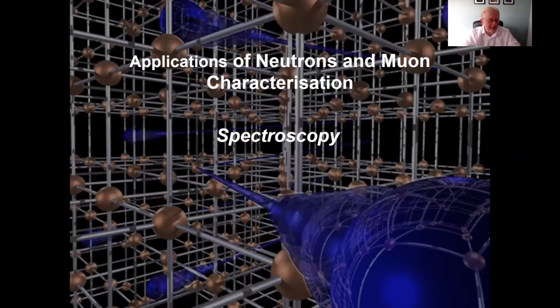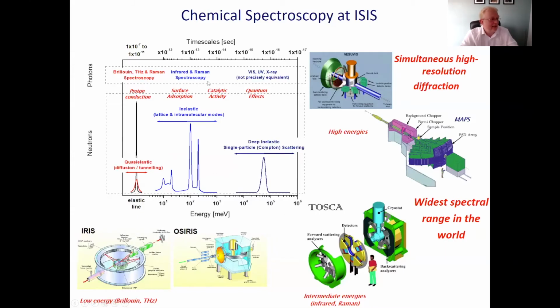Neutron spectroscopy is essentially an energy loss process. So what we're looking at is inelastic scattering with atoms, with nuclei, and we look at the energy that the neutrons lose in that inelastic scattering. And what it allows us to do is think about the motion of atoms within a solid or a liquid, or even on occasions a gas. And in terms of how you might consider neutron spectroscopy, it's very similar to IR and Raman spectroscopy, apart from one very significant difference.